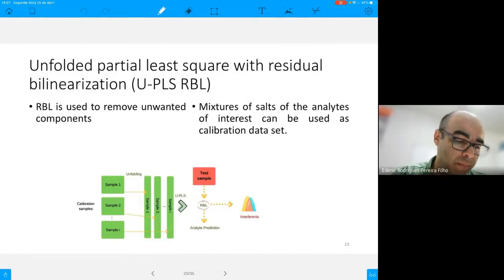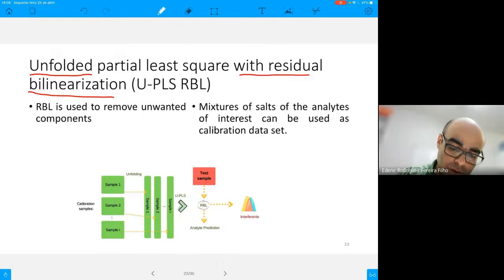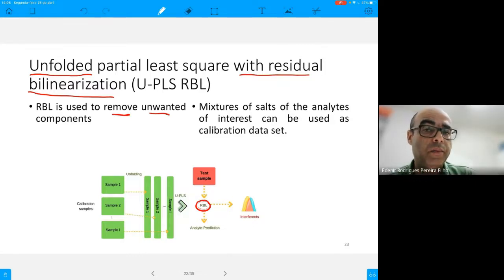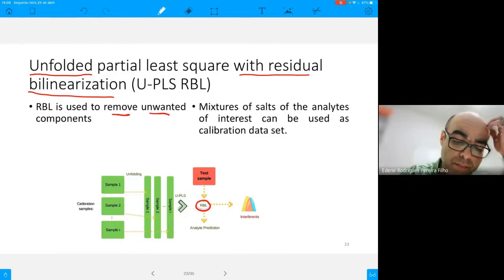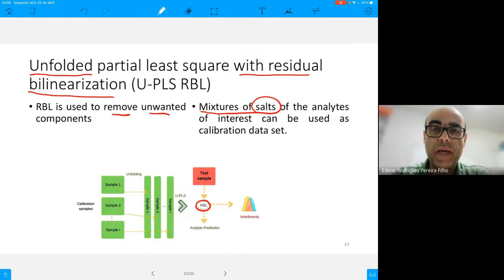In the last year, we developed, or better, we used a chemometric strategy named unfolded partial least squares with residual bilinearization. The main goal of this calibration strategy is to perform a residual bilinearization at the end of the model in order to remove unwanted components. We can improve the figures of merit of the analytical method. And we can also use a mixture of salts in order to have a calibration data set. In PLS, for example, it's necessary to have a calibration data set with the same matrix of the samples.